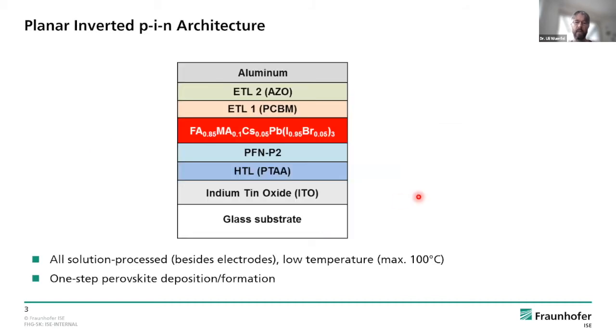I show you some experimental results, and I thought it's good maybe that you just get a small overview of how they were made. It's based on a glass substrate with indium tin oxide, and then we use different hole transport layers, hole transport materials, which extract holes from the photoactive absorber, which is here a mixed cation mixed halide perovskite as the central absorber unit, and then we have also two different electron transport layers, which extract electrons from the absorber, and finished by an aluminum top contact. All these layers are deposited at low temperatures and under ambient air, except for the electrodes.